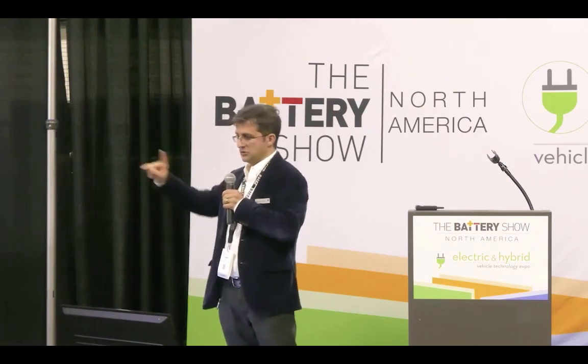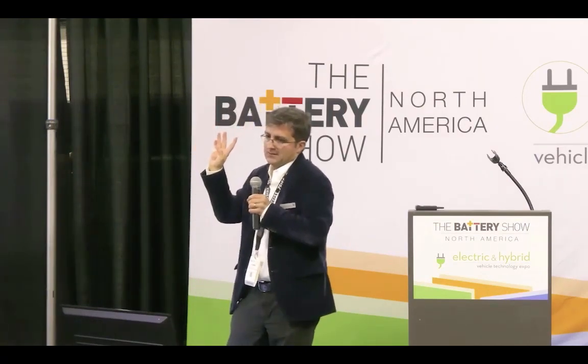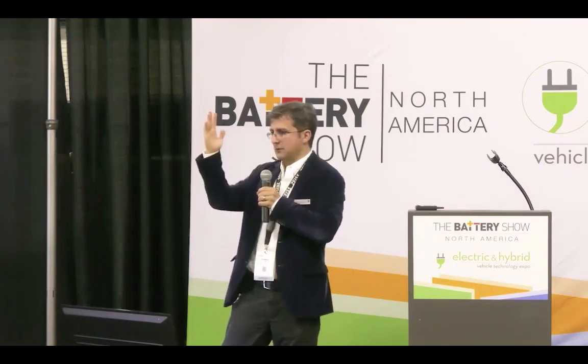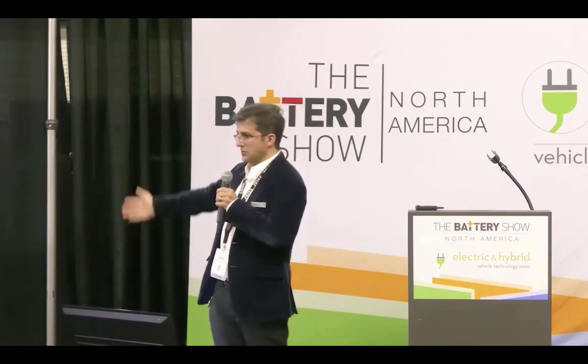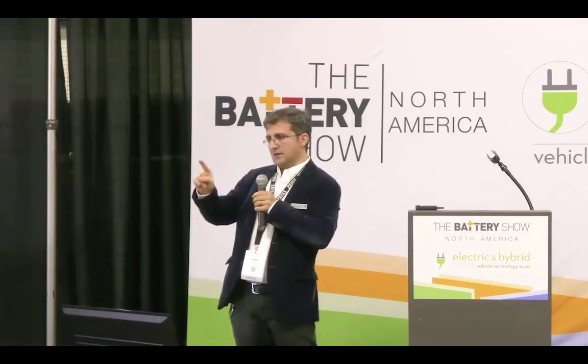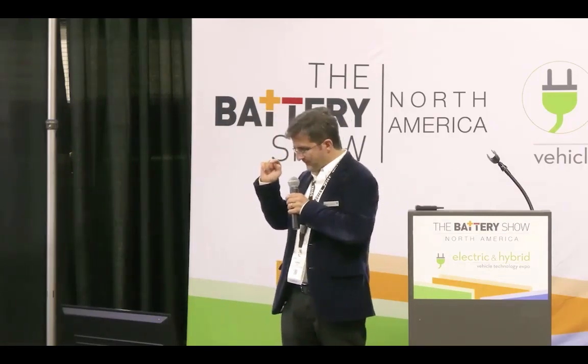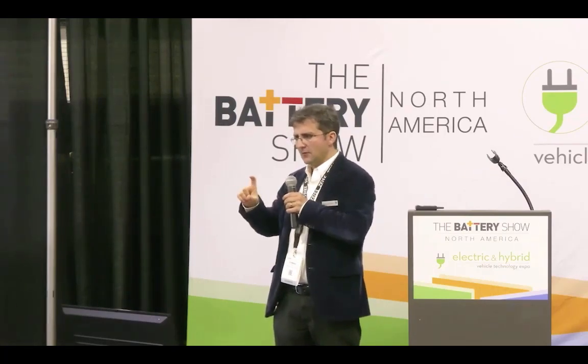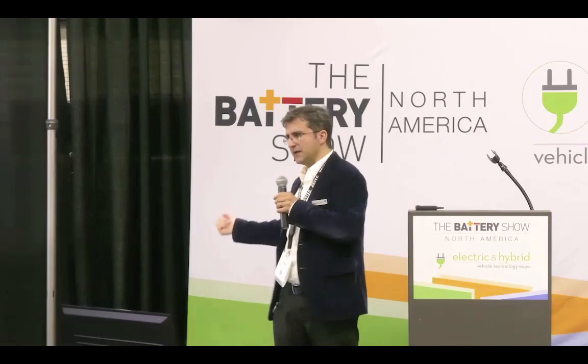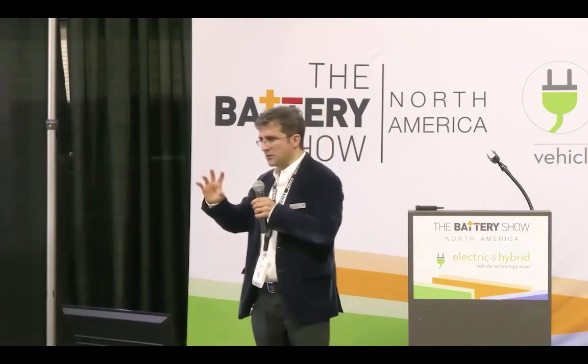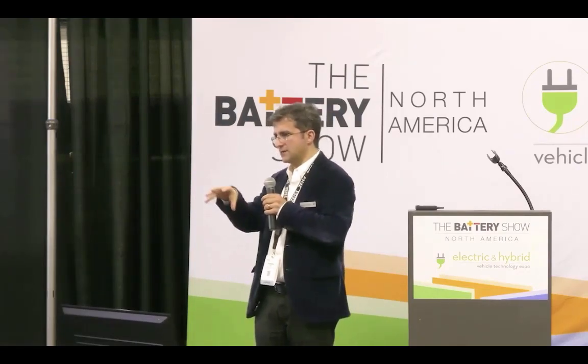You cannot predict how long the battery is going to last by just doing a scan of a fresh battery, because it's going to give you everything looking pretty and beautiful. So you have to do the experiment. And it would be ideal in X-ray technology to have some kind of in situ testing in which you do the charging and discharging of the battery inside, so you don't have to take it out to do the charging. We're working on some of that technology to enable full charging and discharging inside of the X-ray CT scanner.